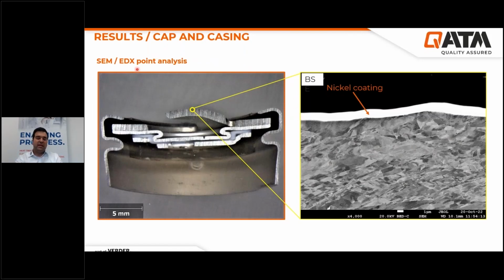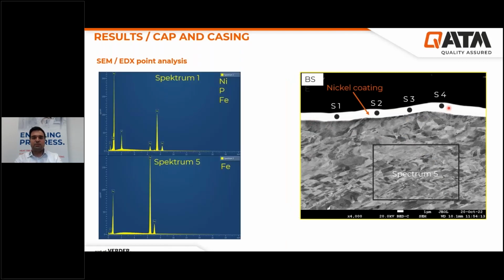Here we can see the result under scanning electron microscope and also under the EDX detector. As before I have said, we have here the base material and the coating on the material. With the EDX point analysis, we can figure out that we have the nickel phosphorus coating on the base material. And as you can see here, we can do the point analysis, and also we can do the EDX analysis on the complete region. And we can see here is the iron-based material steel, and we have the nickel phosphorus coating on it.